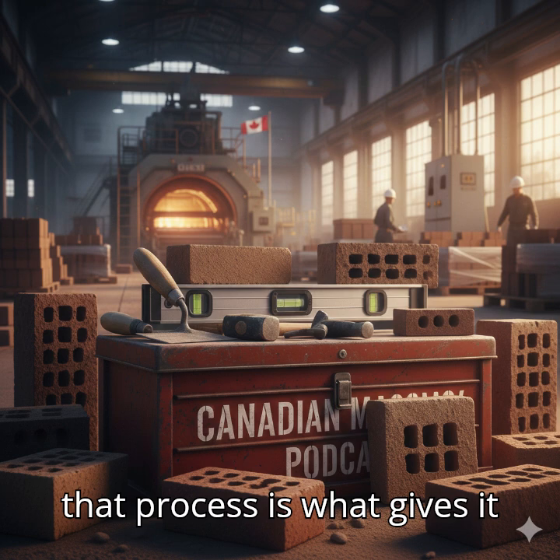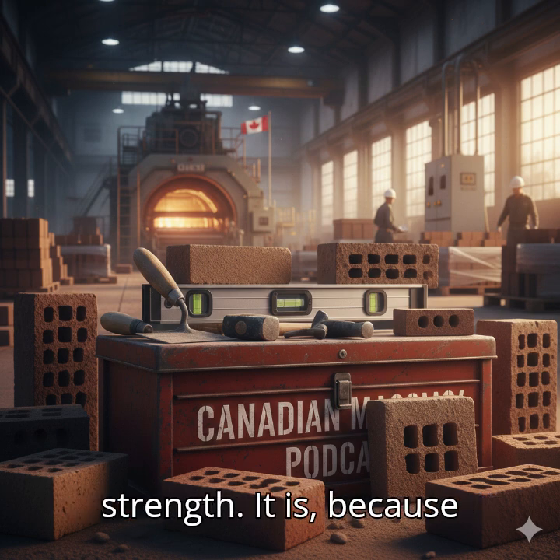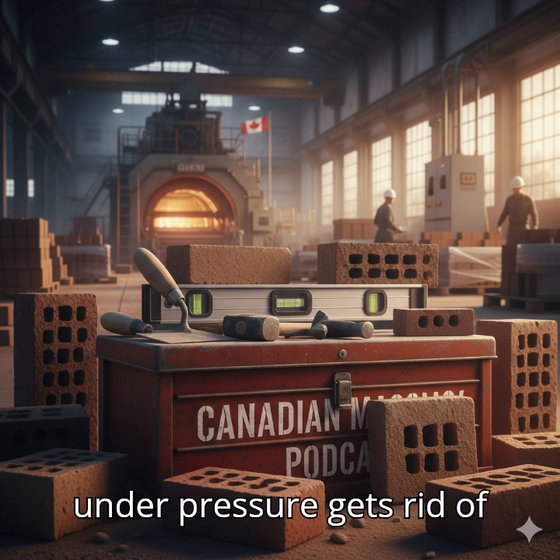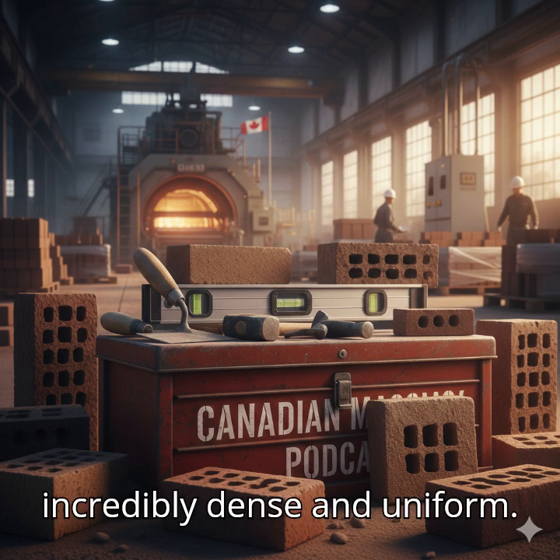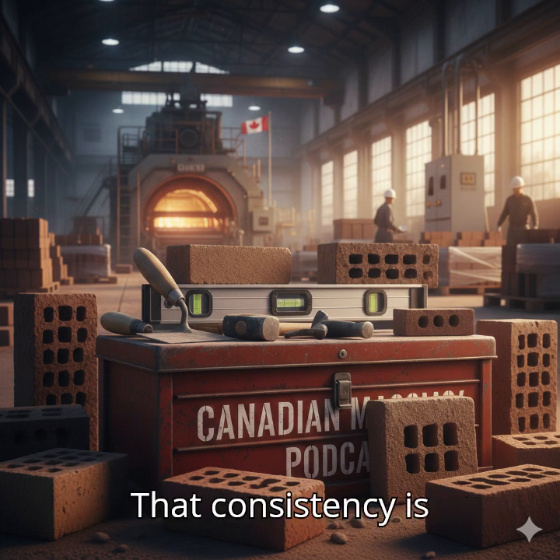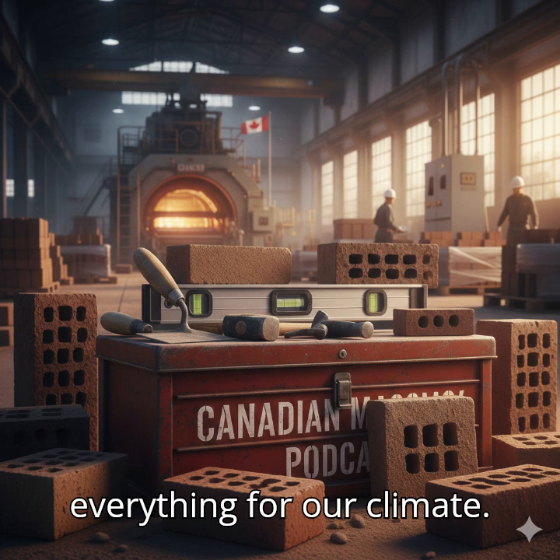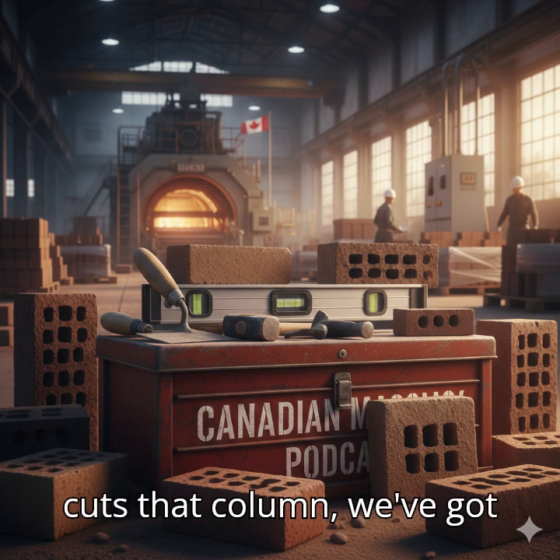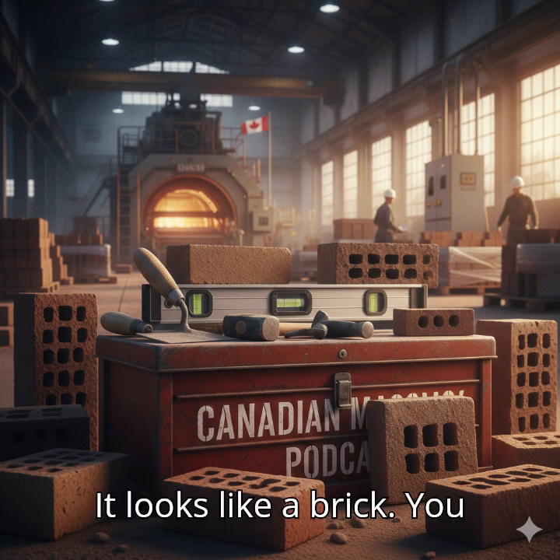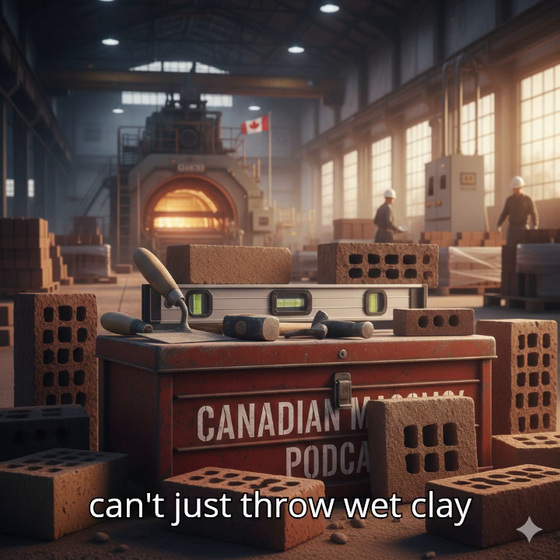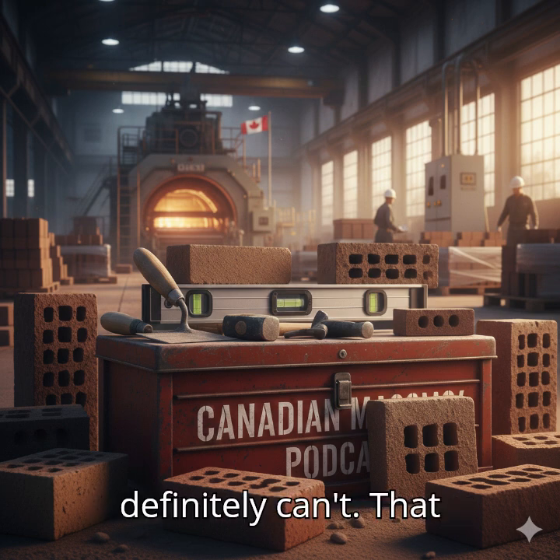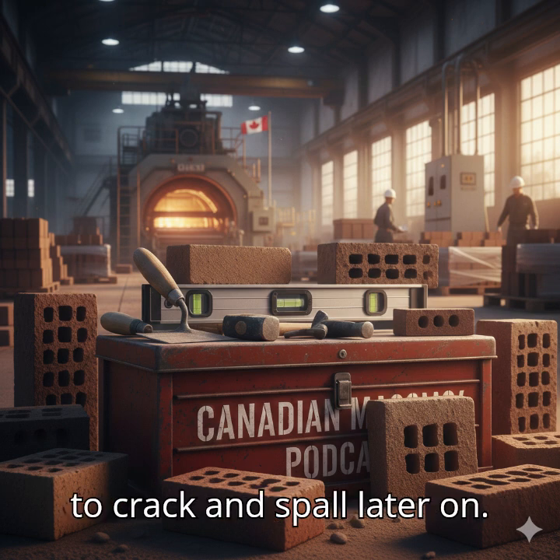And that process is what gives it the highest compressive strength. It is, because forcing it through that die under pressure gets rid of air voids and makes it incredibly dense and uniform. That consistency is everything for our climate. Okay, so once the machine cuts that column, we've got what's called a green brick. It looks like a brick, but you can't just throw wet clay into a wall. No, you definitely can't. That moisture would just cause it to crack and spall later on.